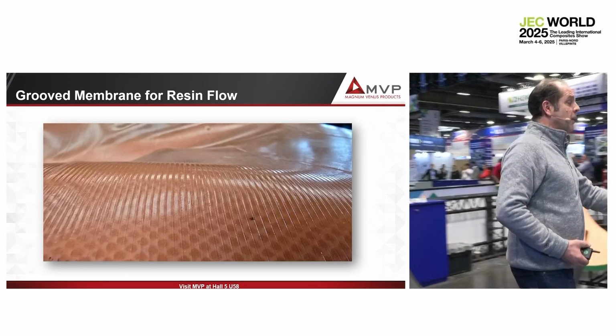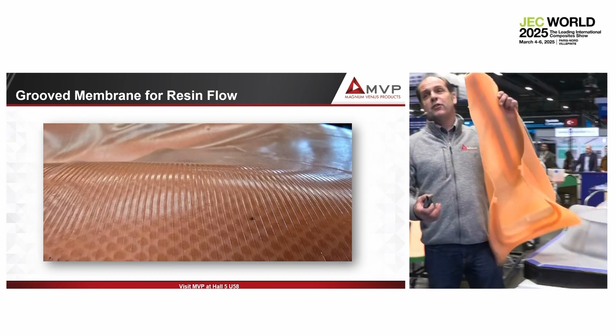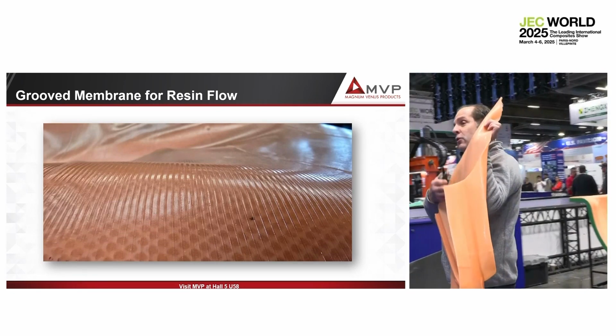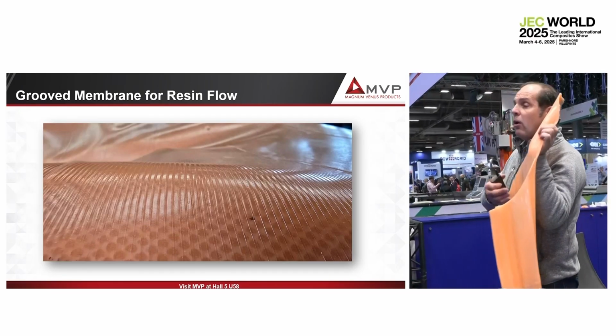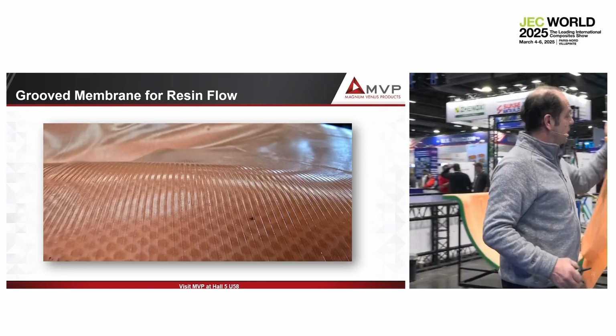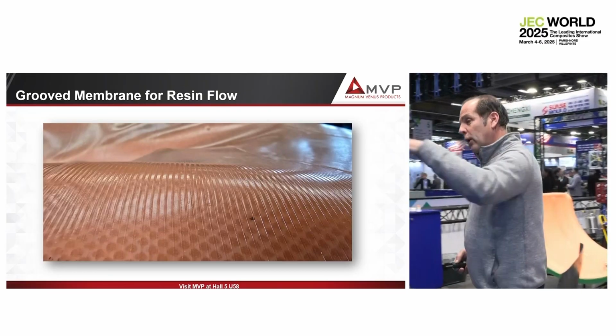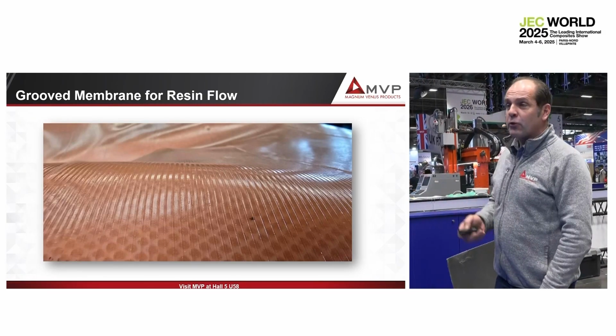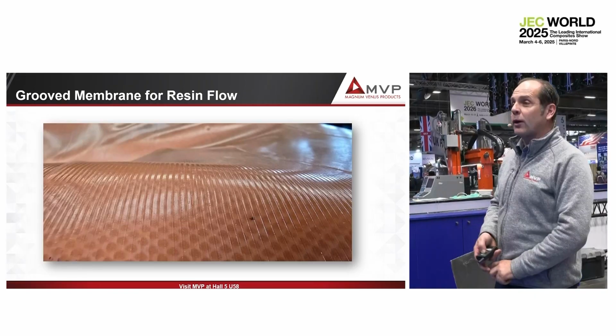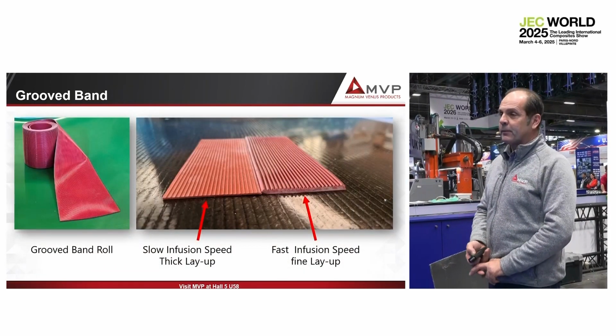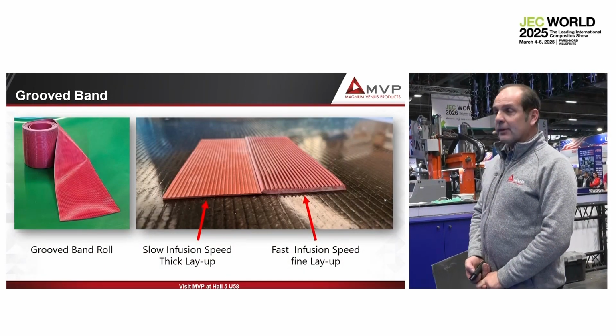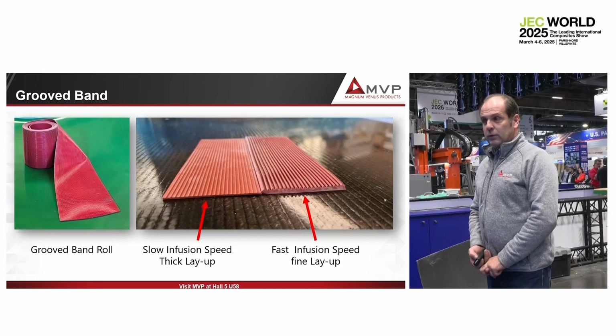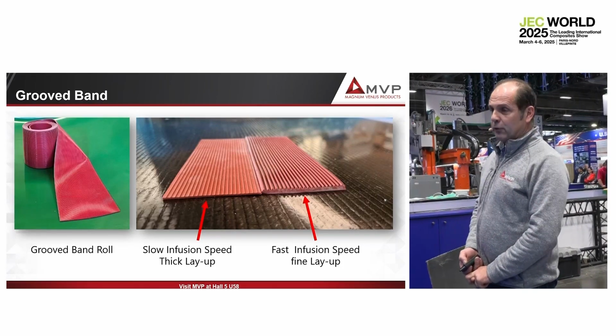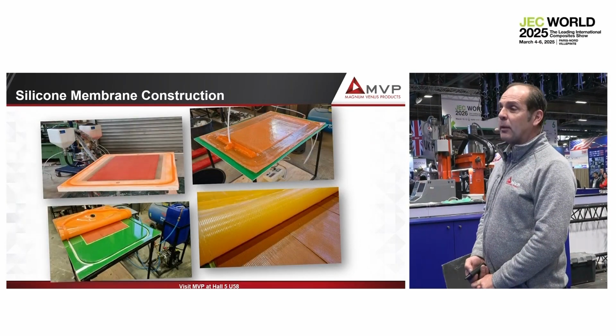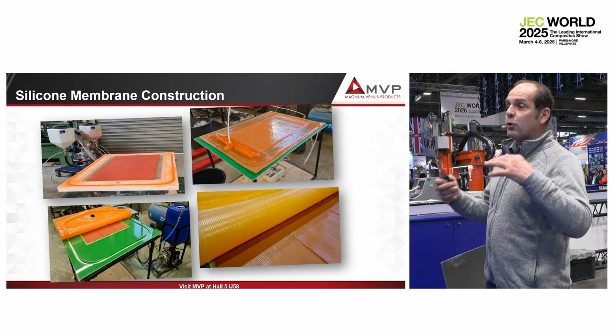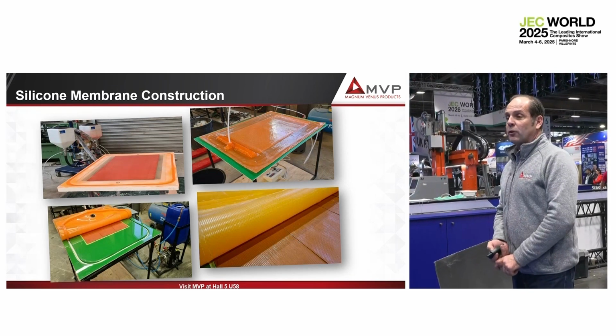If you look at that silicone bag, like many silicone bags, it's flat. So the resin will flow into the injection mat or into a net that you will put, as we do here on the demo with Aerovac, to help the resin flow. Here we don't need it because the resin flows on the little grooves that you have on the silicone membrane. So for that we have a special band and we have different sizes of groove, fast or slow infusion. We load that, it helps to calibrate the part thickness and then to create the groove on the silicone after building the silicone bag.